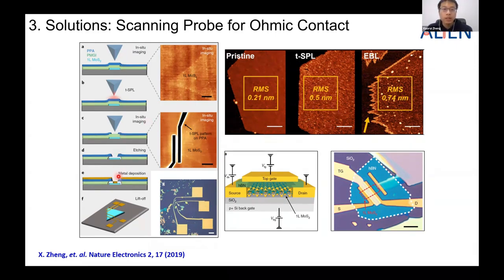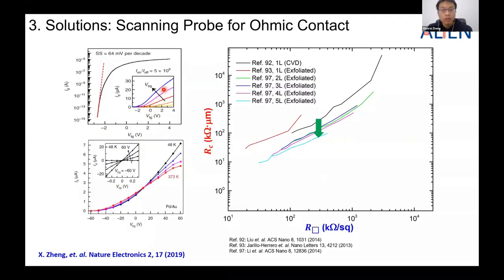Okay, by using this lift-off technique, we fabricated both back-gated and top-gated transistors on monolayer MoS2 flakes, either from exfoliated samples or from CVD grown samples. So if we look at the results, we can see the on-off ratio we achieved on monolayer MoS2 is as large as 10 to the 9, and we can achieve an SS factor of up to 64 millivolts per decade. These are very good numbers for a monolayer transistor.